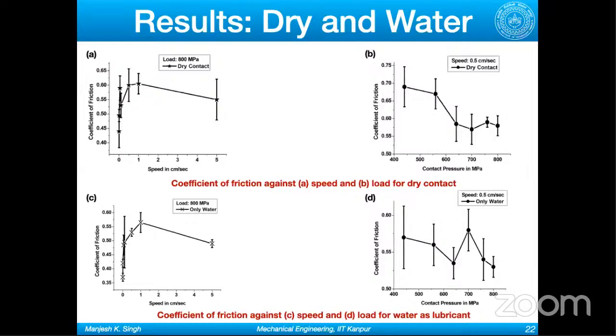So first we started with the dry contact. Always on the left side, you have friction coefficient against speed at a constant load of 800 megapascal. When I say 800 megapascal, I have calculated the Hertzian contact pressure, because I know the materials in contact and the geometry. So whenever I say the load in this part of the talk, it's basically the Hertzian contact pressure. In dry contact, against both speed and load at a constant speed, we see a pretty high friction value, which is expected. When I did it in just pure water, we also get similar friction. As we know, water cannot help us in reducing friction because it cannot support normal load. It will just squeeze out, and you have again metal contact, or hard surface contact.